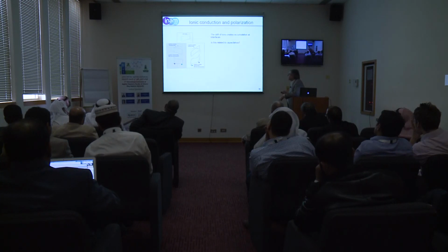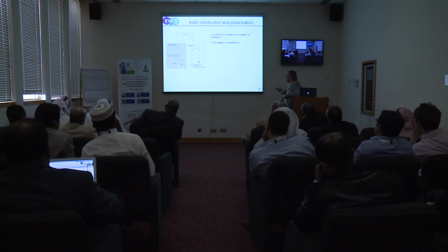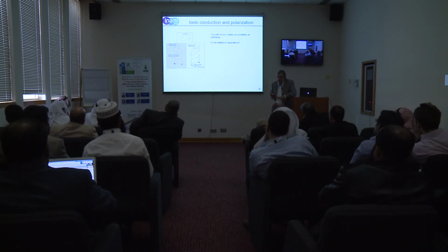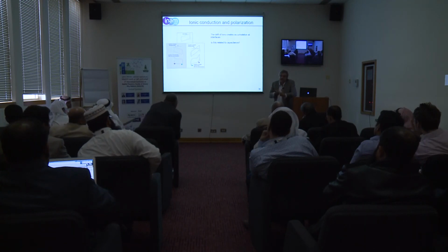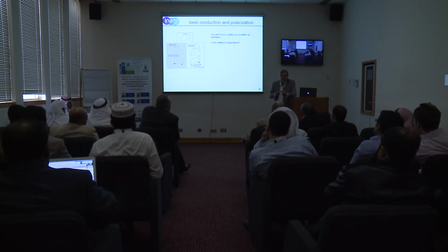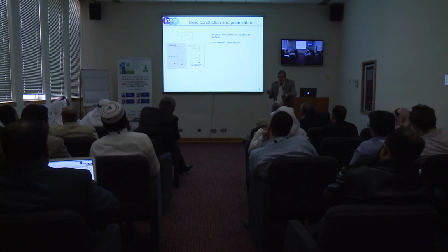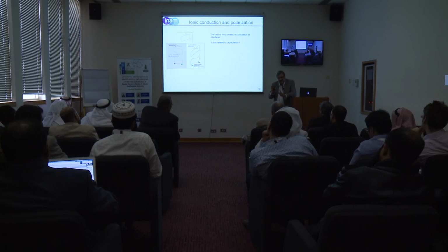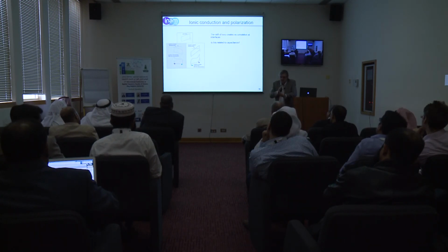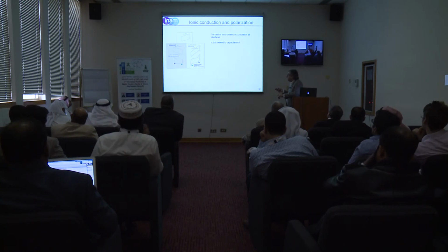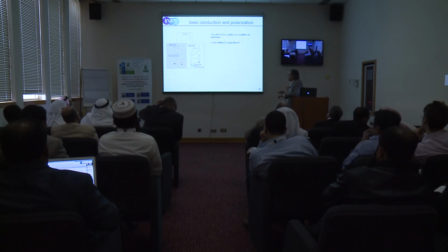But anyway, this is the picture in total, so that my first conclusion is that these changes in the perovskite solar cell have two origins. One is that you have transients because of capacitive effect. Another one is that you have temporary modifications, slower, so the capacitance is scaled a little bit like 0.1 seconds or so. But then you have still slower phenomena, which is moving the ions and modifying the contacts, like in one case this one, in the other case the other.